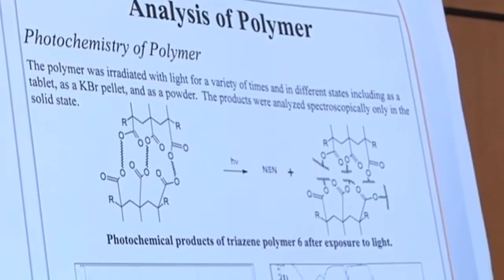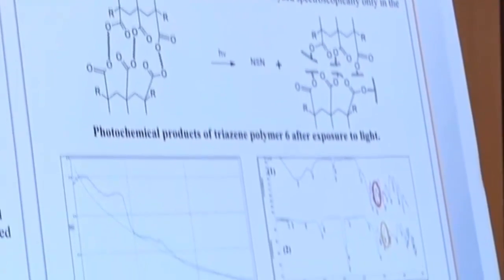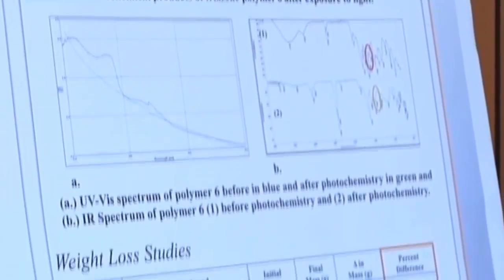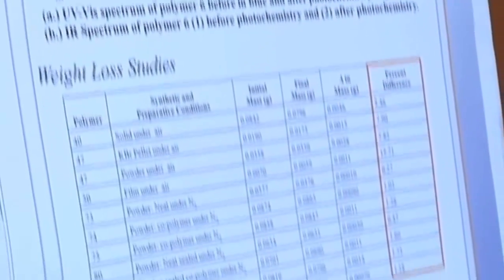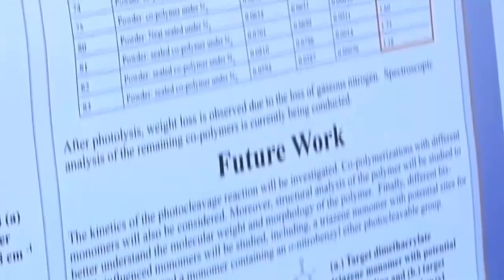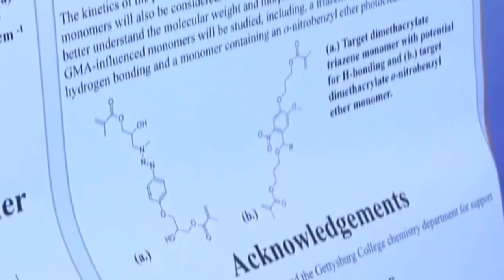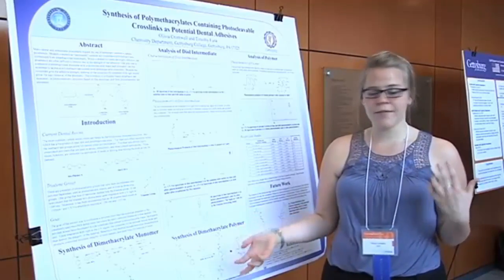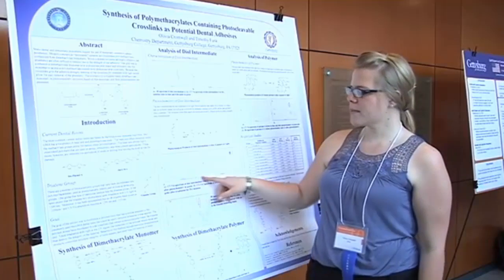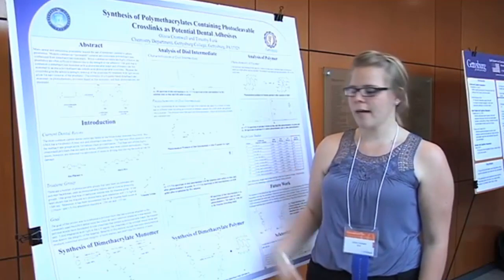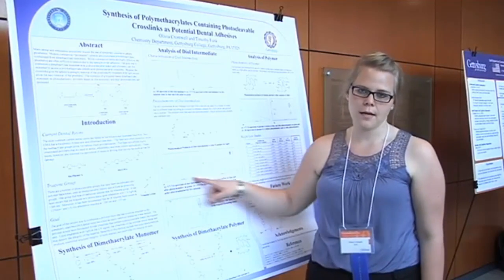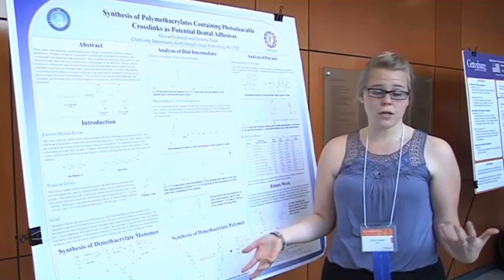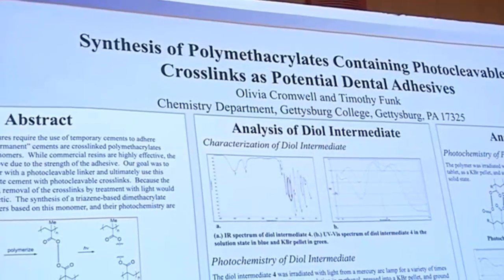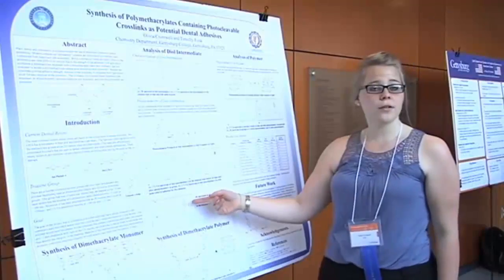Then we took our diol intermediate and irradiated it with light for a given amount of time and in a few different states. So we studied it as a pellet or a tablet and in solution, and we studied what it looked like after. Here's our spectrum before. We see our two diagnostic triazene peaks, and after there is no peak, which was exciting because photocleavage occurred. We also saw this in the solution and solid state, and we saw it in the IR spectrum as well.